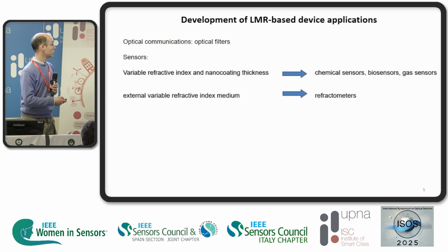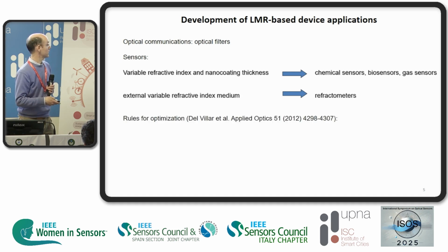If we pay attention to the external refractive index, then we develop refractometers. But refractometers are not a highly interesting topic because there are many commercial devices and it is difficult to compete with them, though our refractometers reach a very low limit of detection of around 10 to the -6. In addition, with optical refractometers, we can monitor not only a single wavelength but different wavelengths. The rules for optimization of these sensors were summarized in 2012.